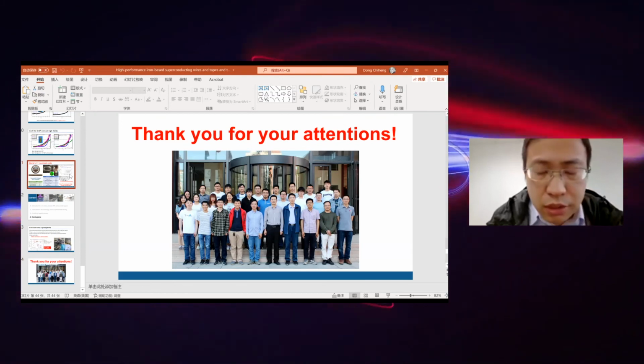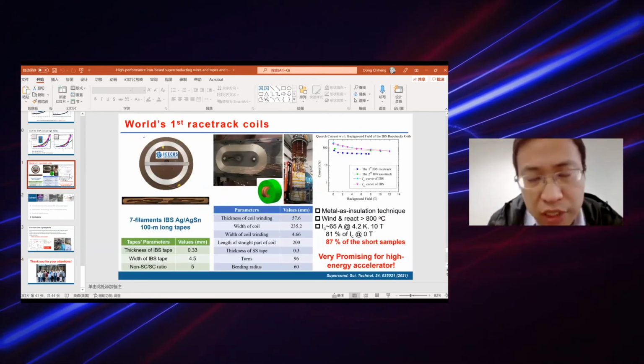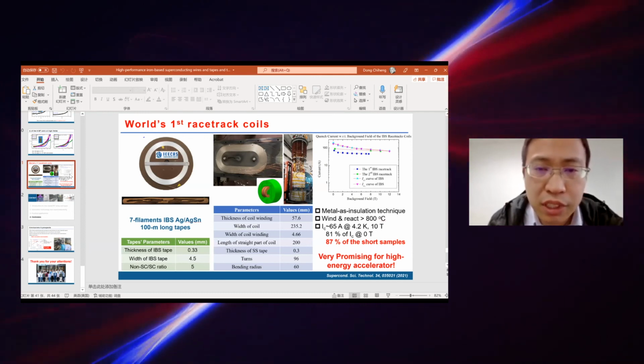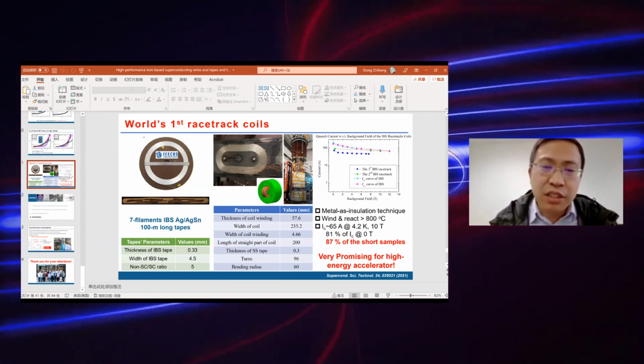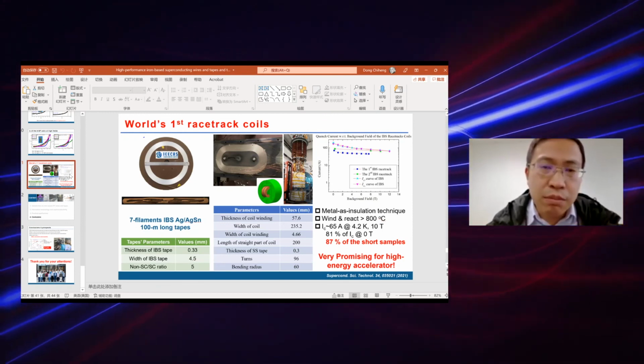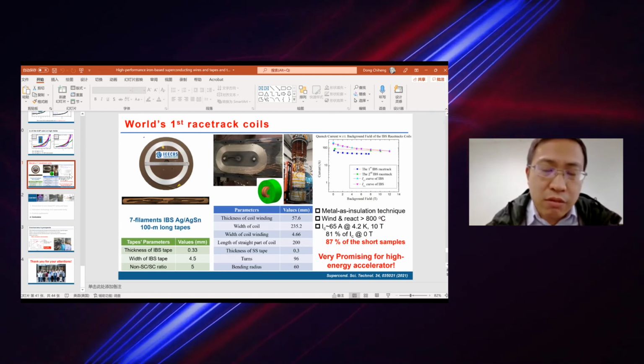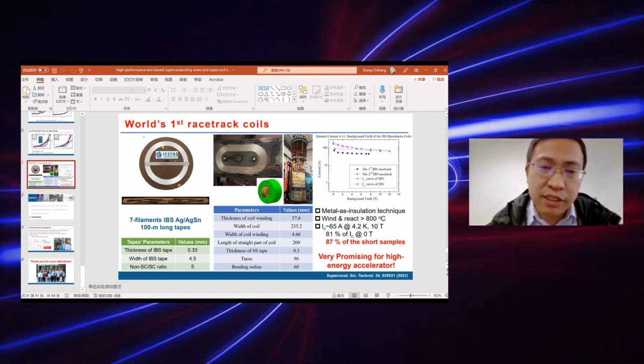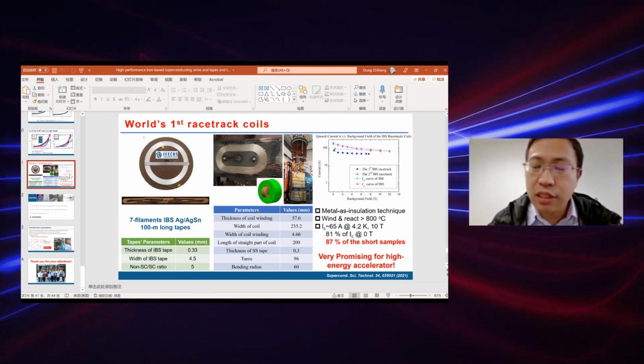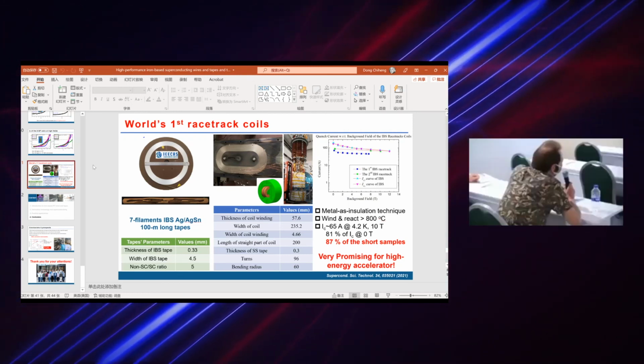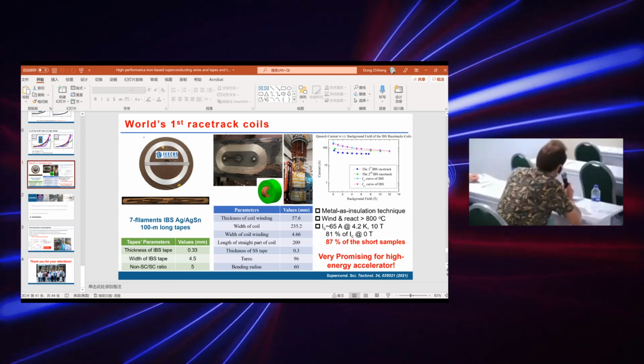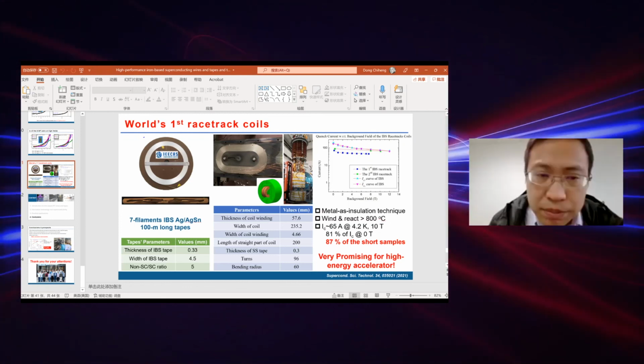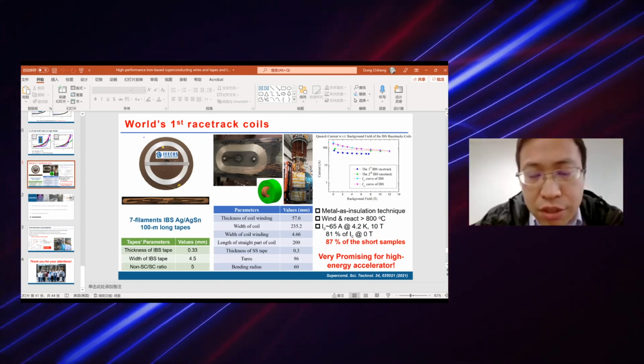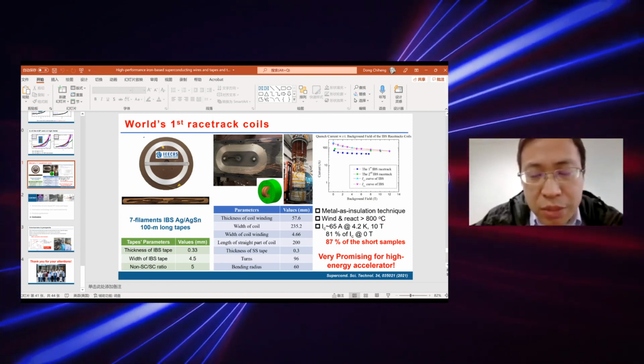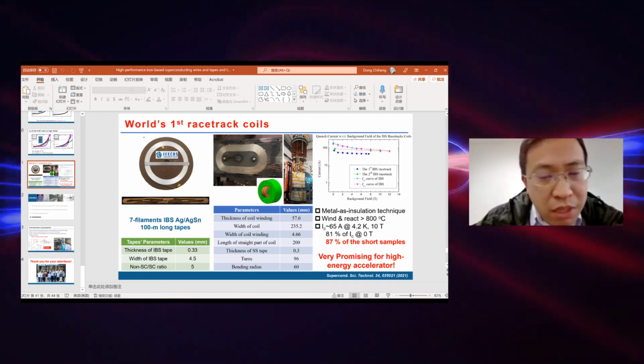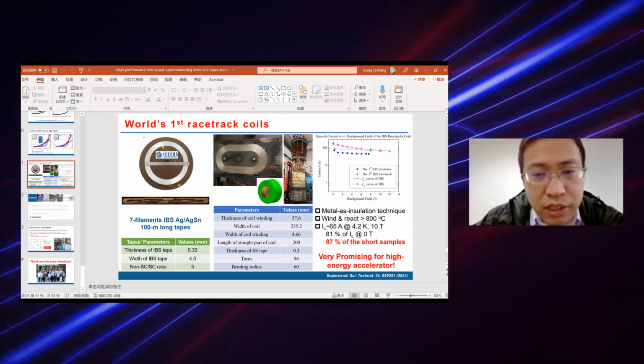Oh, actually, the hot pressing method can only be applied to short samples because the device is limited to about 10 centimeters. So for the long wires, we can only use a flat rolling process. Flat rolling is actually what we are using now. But in our next step, maybe we can use hot isostatic pressing to increase the core density.